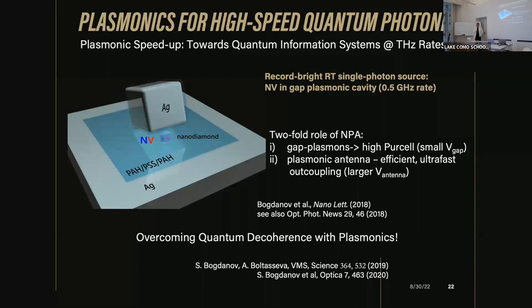But nanopatch antennas are very different in that regard. All the energy is confined in the gap, and the gap could be very small, as I pointed out, but the antenna itself could and should be relatively large, like 50 or 60 nanometers, as our calculations show. Then it outcouples photons very efficiently, with a rate that could beat not only the decoherence rate, but potentially also the rate with which plasmons decay. Because everybody says plasmonics is lossy.